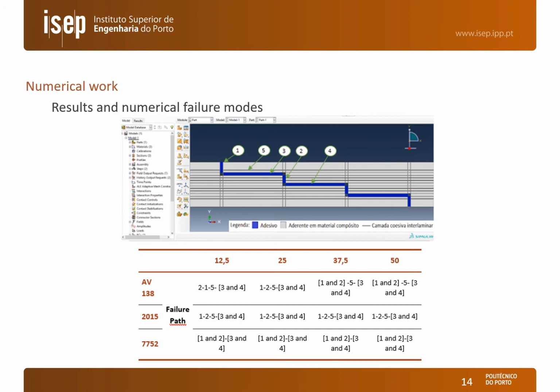We can see in the table a summary of the failure modes observed for each of the 3 adhesives and for the different overlap lengths. We can see first-hand that the 7752 did not show interlaminar failure, which is denoted by the number 5, while AV138 and 2015 had interlaminar failure of the composite during the failure process, but it should be emphasized that final failure was always taking place through the adhesive cohesively.